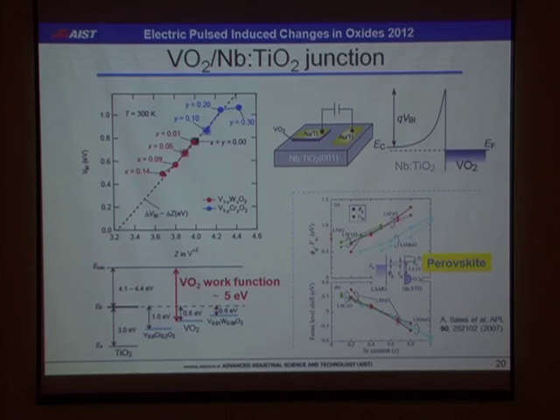The work function of VO2 is approximately 5 electron volts. And this is consistent with the reported value. And by electron doping, it can be reduced and increased by hole doping. Actually, this work function is one problem. So all metal electrodes have an ohmic contact against VO2. Even platinum has an ohmic contact to VO2. So far, we haven't succeeded in making a Schottky junction between the metal electrode and VO2.